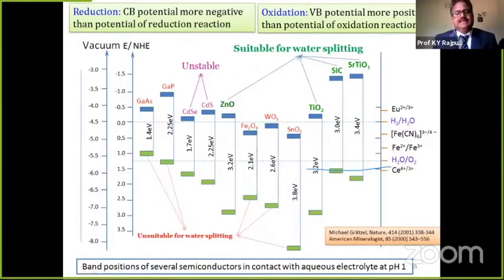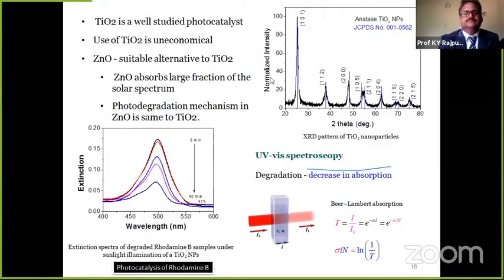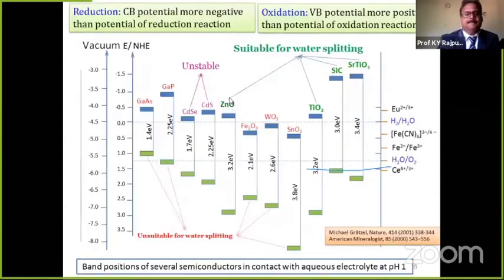There are various semiconductors that can be used as the photocatalyst. Here, I have displayed the band positions of several semiconductors in contact with an aqueous electrolyte at pH equal to 1. So as I mentioned, for using a semiconductor in photocatalysis, its valence band edge should be below the oxidation potential, and the conduction band edge should be above the reduction potential. This is the thumb rule.